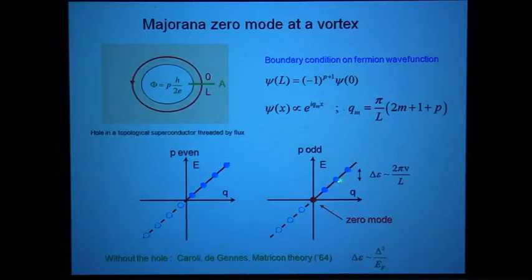So in general, if you have a superconductor where the Fermi energy is much bigger than delta, then these states are going to be very finely spaced. What you'd really like to do is make this Fermi energy as small as possible. So maybe if you could tune the Fermi energy to a Dirac point, then this level spacing would not be so small.